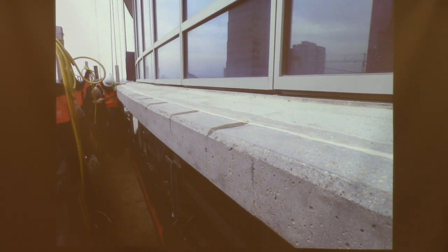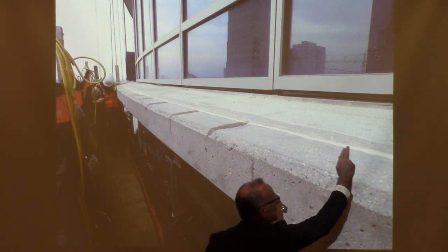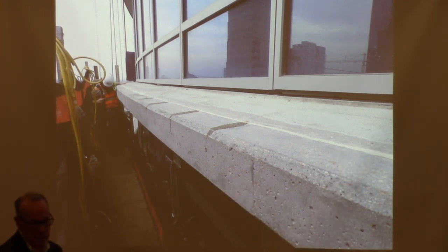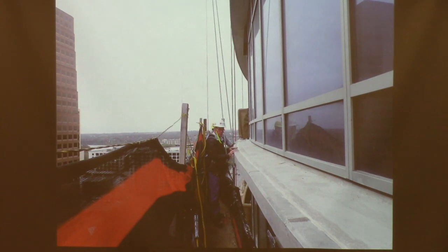And then once we removed the concrete, when you have new concrete to old concrete, you're going to get a tendency to get very small shrinkage cracks. It's just inevitable. And we had provision to fill those with methyl methacrylate before they came back and put the waterproof coating on. And you also see a sealing point right at the intersection there, that we knew would be an area where we would tend to want to crack. And of course, the waterproof coating is going to come over there, so that provides kind of an elastic area there for the membrane to be able to bridge.